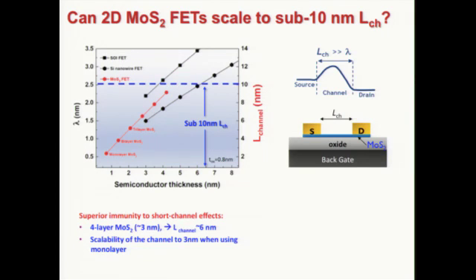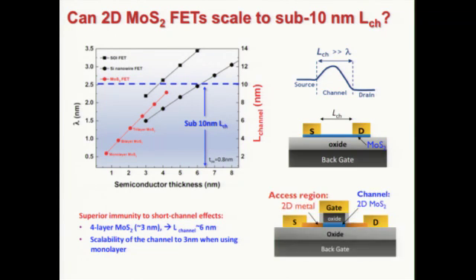basically the lateral source-drain electric field is 100% confined in the channel, so that the source-drain electrodes are thin enough so that all the electric field goes through the channel, not through the oxide or the surroundings. That's very important. It's not a big deal in long channel transistors. We can use a very thick metal layer as source-drain contact. But in a short channel transistor, at this dimension, we have to add some access region, an ultra thin access region, to contact the 2D channel. So the idea is that if you are using a 2D channel, the contact should also be 2D metal, or at least a very thin contact.